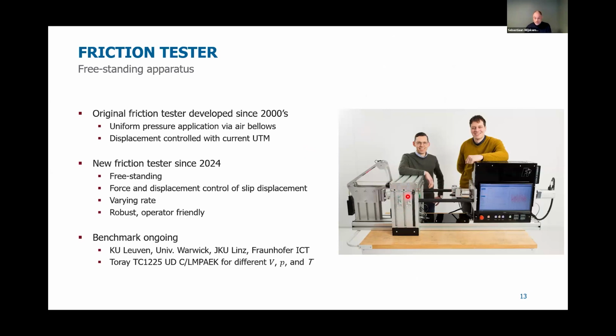The pressure is very well controlled here, because if you have any misalignment between your platens, then you will generate pressure peaks that will mess up your measurement. So a lot of attention has gone to that. It's a very stiff, non-compliant setup. We can pull with kilonewtons at least without any movement of the machine itself. We can do this by force and displacement control, so that adds more possibilities for research into stress relaxation, for example, and creep type of measurements. We can vary the rate, so accelerate or do steps, and it's very robust and operator friendly.